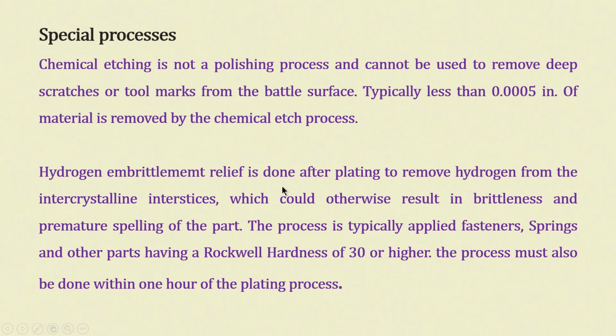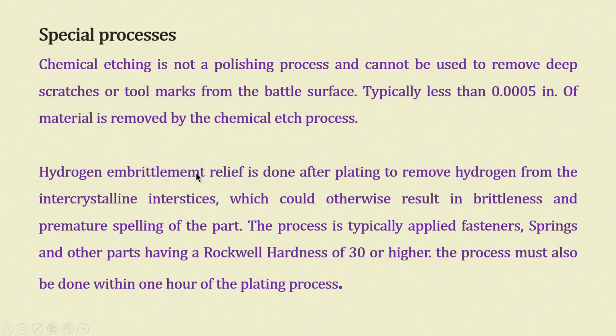So, hydrogen embrittlement relief. Quite often, whenever you are doing electroplating, acids upon reaction with the metal generate hydrogen. This hydrogen gets into the metal matrix, the metal plates, either cathode or anode. The hydrogen going inside the metal causes the metal to become brittle. That is known as hydrogen embrittlement, a very well known process. A lot of research work has gone into the study of hydrogen embrittlement, and relief is done after plating to remove hydrogen. So, we have to do hydrogen embrittlement relief operations to remove hydrogen from the intercrystalline interstices that could otherwise result in brittleness.